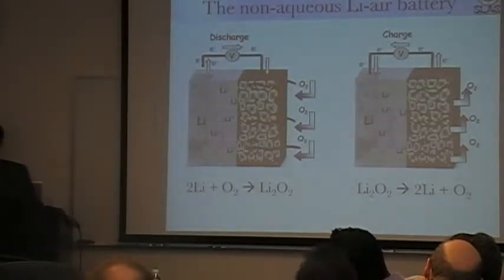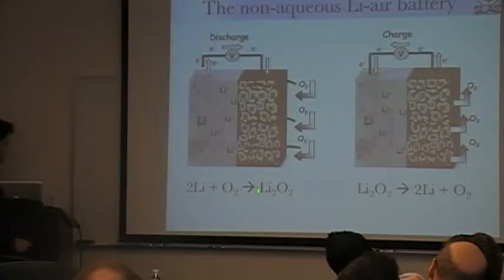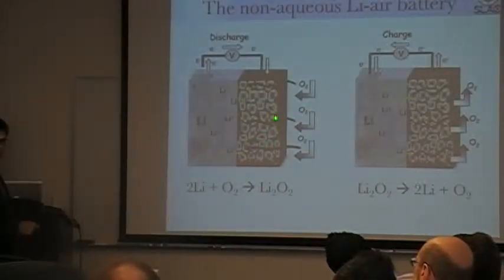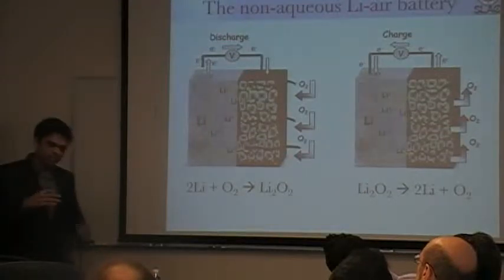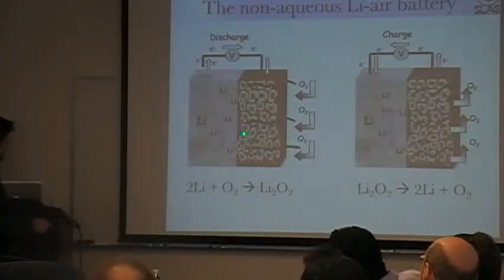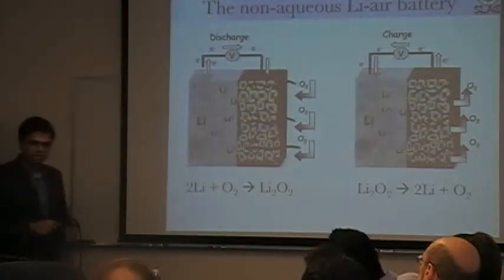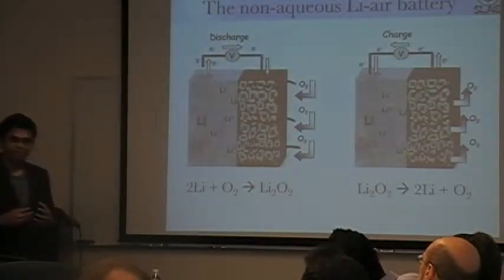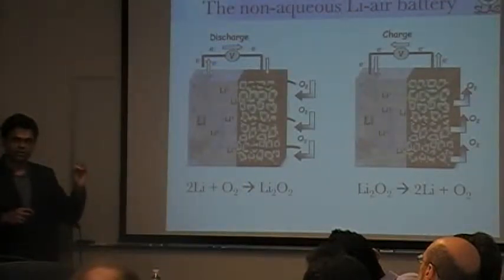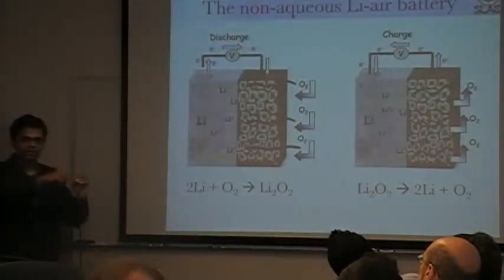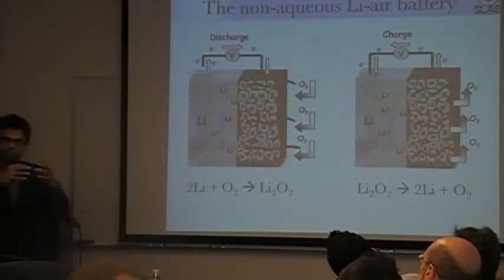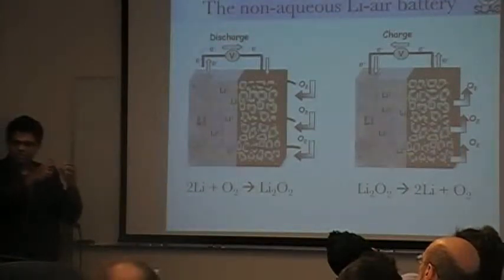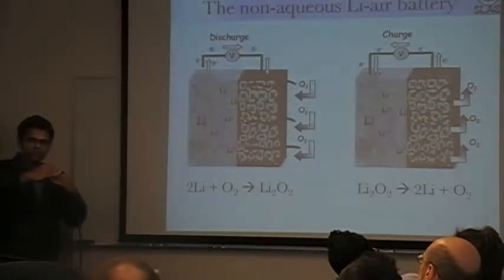What is important to note in lithium-air batteries is that lithium peroxide is insoluble in the organic electrolyte solution used. So what that means is when you discharge the battery, you are essentially growing thicker and thicker films of lithium peroxide. This is different from traditional catalysis where reactions happen at a catalyst particle — here you don't have traditional catalysis.